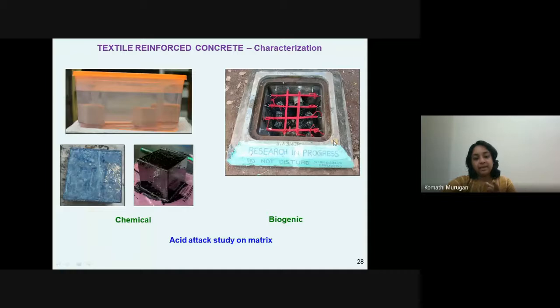In the biogenic sulfuric acid test, what we do is all these cubes, the coated and uncoated cubes, are prepared and they are suspended in the crown portion in certain sewage chambers. So we actually identified certain sewage chambers where there is a good flow of sewage. And in the crown portion, we also checked for the presence of the pH. We check the pH at the crown portions to understand the sulfuric acid, that is the biogenic sulfuric acid presence. So what we did is we suspended these cubes in some of these chambers, and these are monitored.